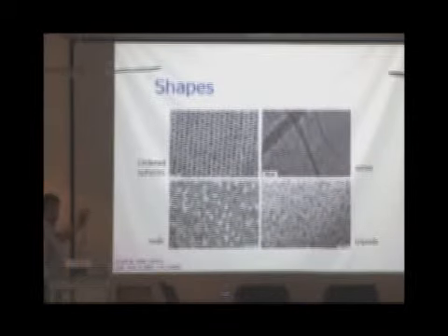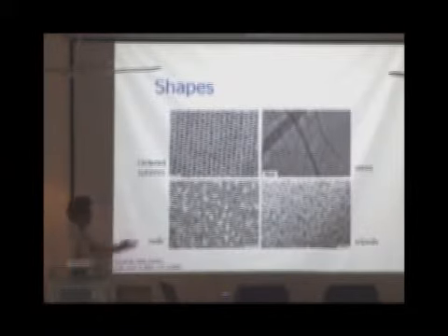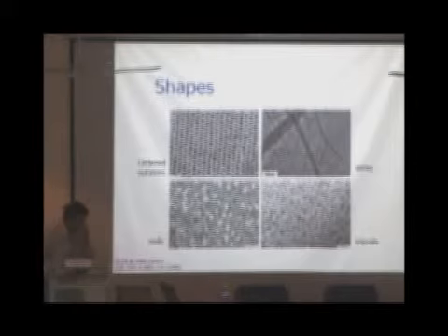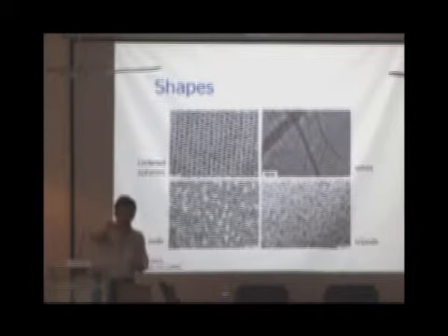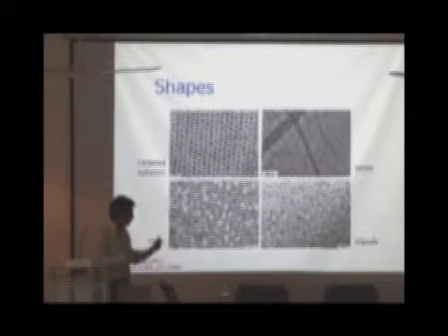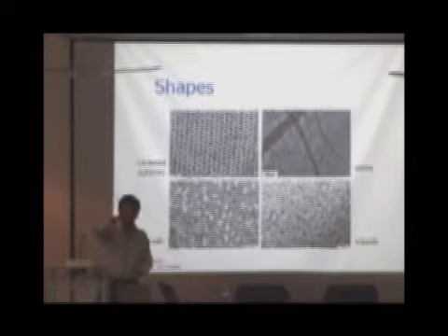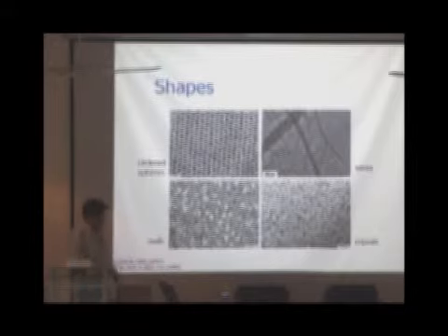We can make different shapes: very monodispersed spheres, wires, nanorods, tripods, and all of them have various applications. For example, think of tripods or tetrapods. If you want to use these materials in LEDs or photovoltaics, you always want a contact, and in a particular direction. If you want the central sphere sitting on the bottom electrode and the rod pointing out, then a tetrapod is the only way to ensure it, because it will always sit on its 3 legs. Okay.